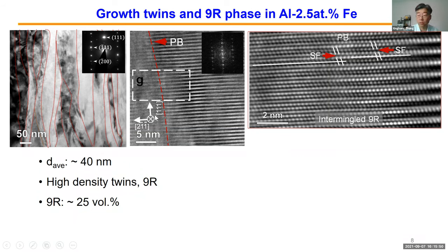And this structure is normally called a 9R phase, based on the high resolution TEM. What that means is, in general, when we look at an FCC metal, the close-packed planes have ABC stacking. But when you introduce stacking faults in the aluminum-iron case, your repeating unit is no longer ABC. It becomes nine repeating layers, so you give it a name, 9R, a nine repeating layer structure. There is basically a Shockley partial on every atomic plane, but they're mixed. You have two screws, one edge, and their interaction is quite interesting.